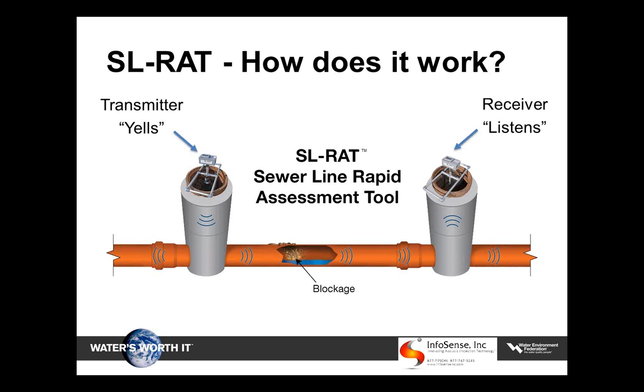The SL-RAT receiver knows what the transmitter is yelling, it knows what it hears, as well as knowing the length of the pipe. It uses this information in a sophisticated pattern matching algorithm to give an assessment of blockage condition in the pipe on a scale of 0 to 10, where 0 equals blocked and 10 equals clear, a pipe that's as clear as a clear reference sample. It does this work without any flow contact and in less than 3 minutes.